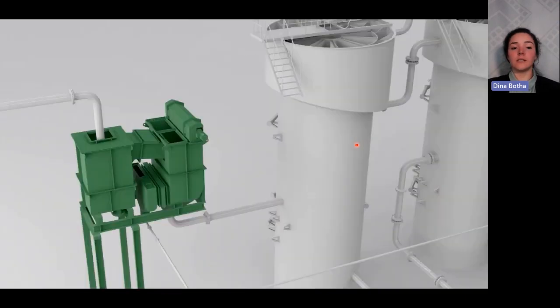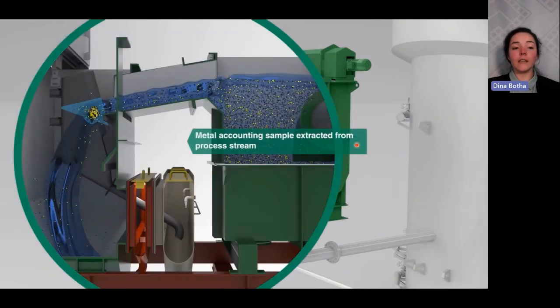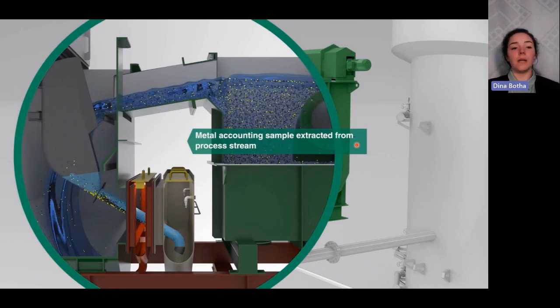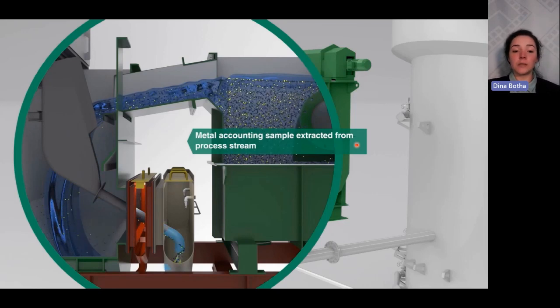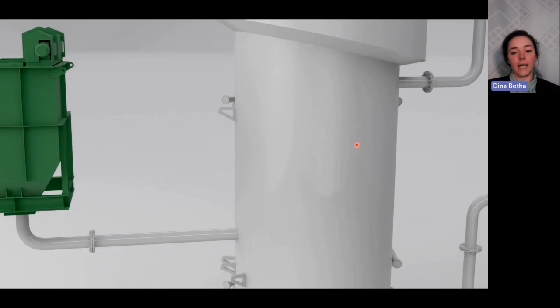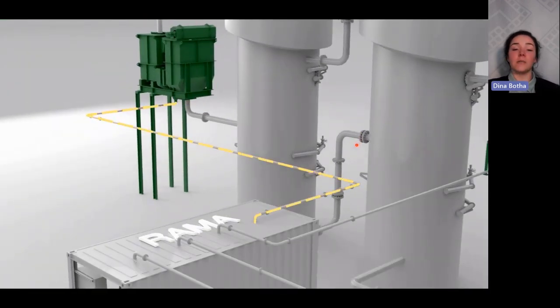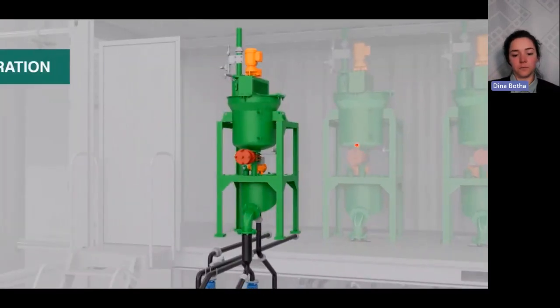The composite sample is taken from your primary metallurgical accounting unit, and this sampler will take a few subcuts every 1 or 2 minutes, depending on your analysis period. These multiple subcuts are then taken to your intermediate mechanically agitated hopper. The mechanically agitated hopper ensures that the material stays well mixed while all the multiple subcuts are collected.